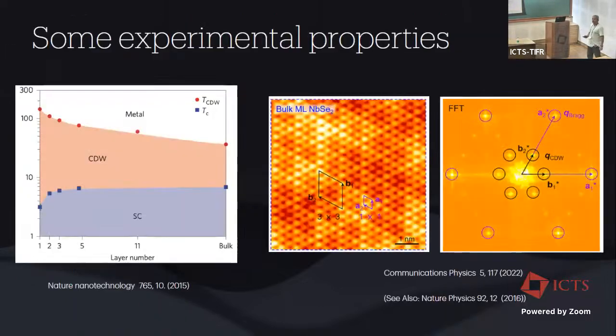Experimentally, also, there have been some very interesting things discovered in the last few years. One of them is that if you start off with a bulk material, and measure the transition temperature for the charge density wave instability and the superconducting instability and reduce the number of layers, one thing that always shows up is that the charge density wave transition temperature goes up, whereas the superconducting transition temperature mostly stays almost unchanged. It shows a relatively small dip as you go over to the monolayer limit.